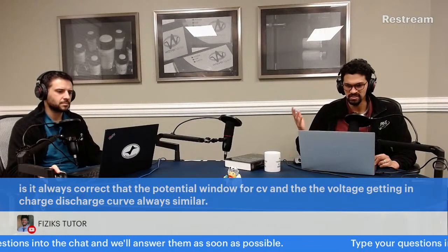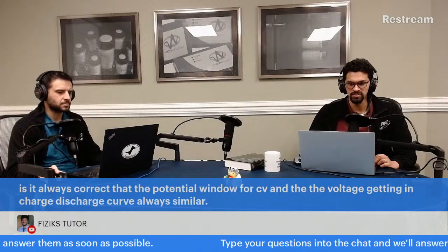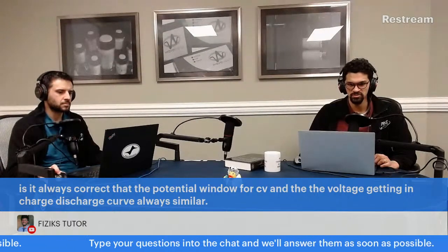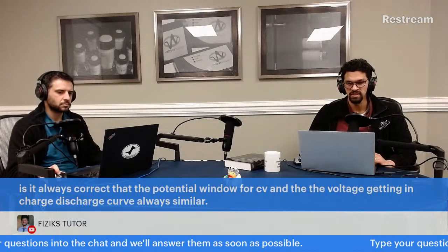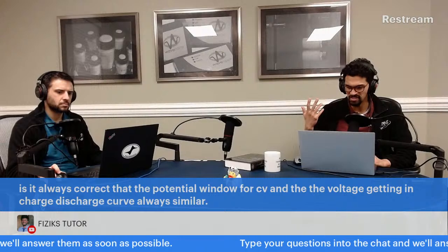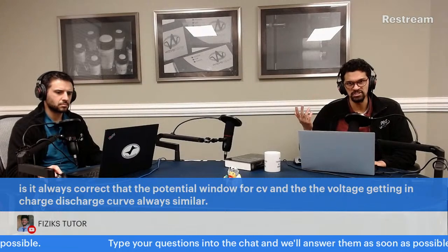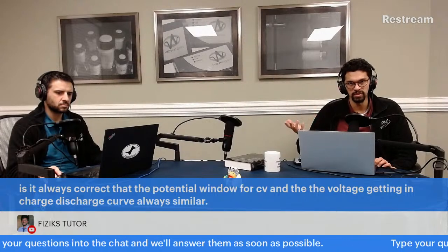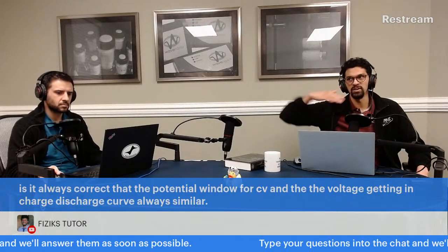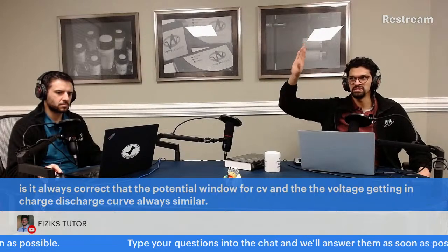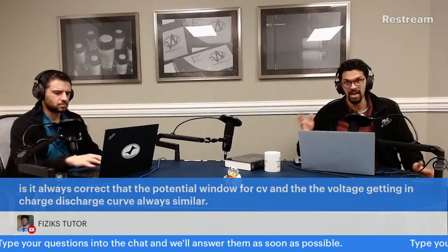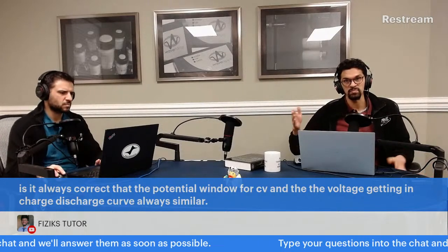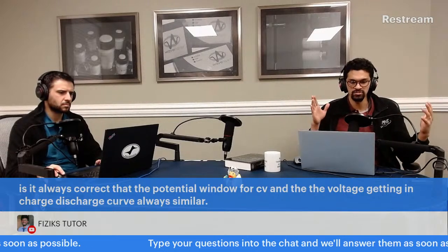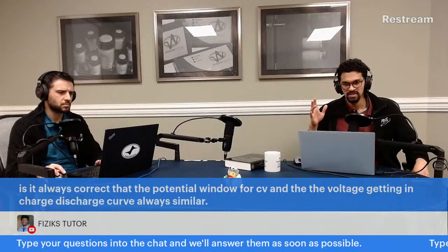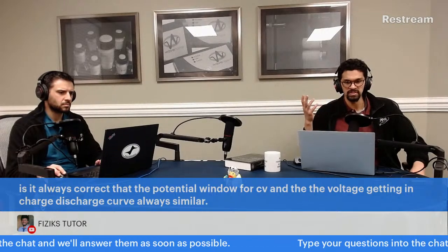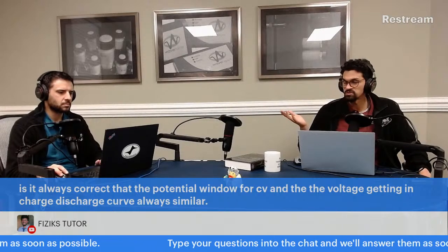Based on what Neil said last week, the potential window for CV and the voltage from the charge discharge curve should be similar. Neil was mentioning last week that there's a little bit of an arbitrary nature to how we define the potential window. You say, oh, I'm starting to get an up curve, so my potential window is here, but what's the real current that you're measuring at that potential, and where are you in your charge discharge curve for your battery? Those are some things to think of. But generally speaking, I would say they're the same.